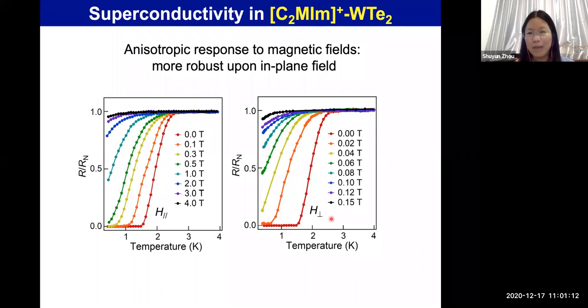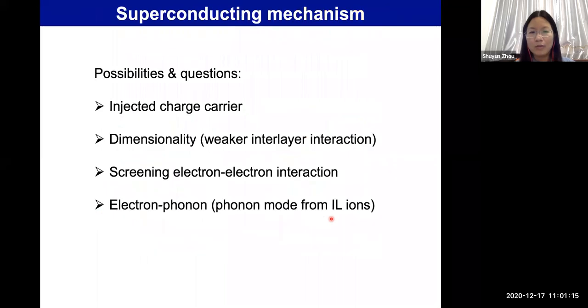So what is the mechanism of the superconductivity? Well, we note that these cations carry charges. So one possibility is that perhaps these injected charge carriers could be important for the superconductivity. And at the same time, we also change the dimensionality or the interlayer interaction of this intercalated sample. So these are the two major issues here. And for the moment, our preliminary results show that this interlayer spacing probably plays a more important role.